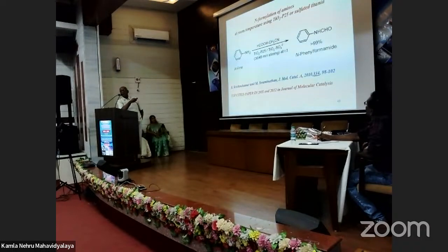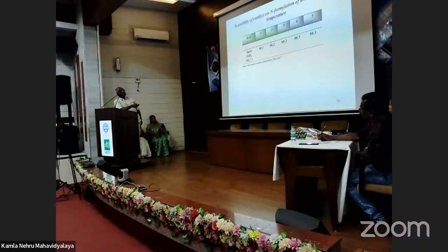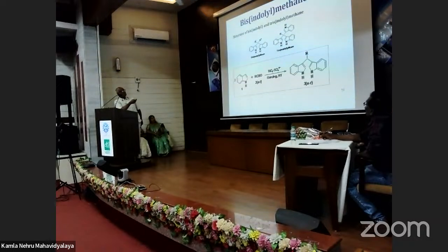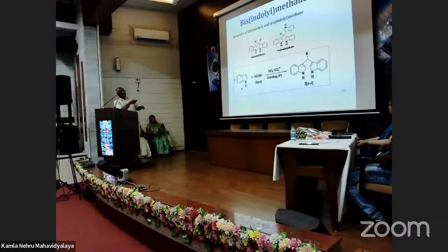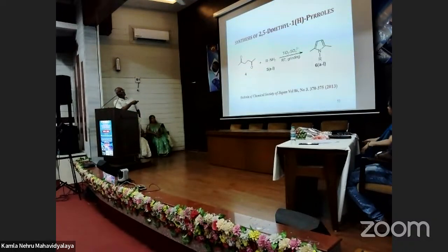And this paper at that time was a top paper in Molecular Catalysis. You can see the efficiency, even after 5 runs, the same catalyst was filtered, dried and reused. You can see 98.3% efficiency even at the 5th run. And this is another reaction using the same solid acid catalyst, sulfated TiO2, a condensation reaction. And this is another reaction, a cyclization reaction using the primary amine, just by room temperature grinding.